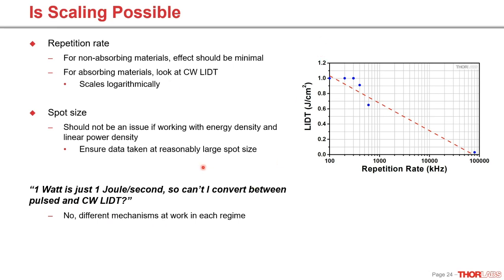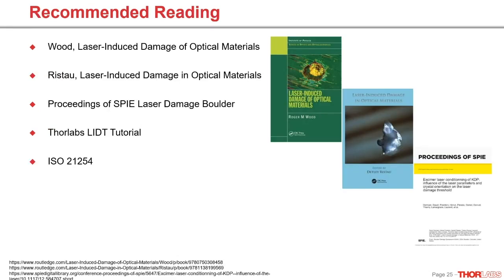And then finally, for those of us who are skilled at unit conversions, I will occasionally hear something like, look, a watt is just 1 joule per second, so shouldn't I be able to convert between pulsed and CW damage threshold? And yes, a watt is a joule per second, but no, you cannot do that conversion because different mechanisms are at work. We're dealing with dielectric breakdown and various ionizations versus thermal effects.